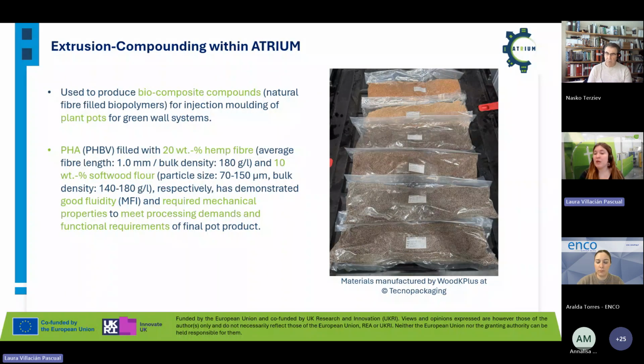Extrusion compounding within ATRIUM, what has been done already is to produce these biocomposite compounds, which are mainly made of natural fibers filled with biopolymers, in this case PHA. And this will be used afterwards for injection molding of the planting pots that will be integrated in the green wall systems. The final formulation that will be scaled up is this PHA. It's a copolymer of PHBV, filled with 20% of hemp fiber.